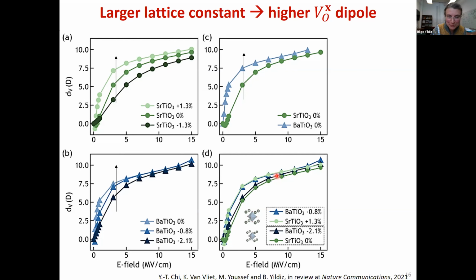So now strain effect on the polarizability under electric field. So the mouthful electro-chemo-mechanical coupling is really embodied in this problem. We're looking at the electric polarization as a function of strain on the defect chemistry of the material. Okay, so that is again the polarization introduced with oxygen vacancy. And now by varying the lattice constant, for example, in strontium titanate, going from compressive to tensile strain, we can clearly see an increase in the net dipole, increase in the polarization. Similarly, by going from compressive to tensile in barium titanate, we see an increase in polarization. Contrasting unstrained strontium titanate to barium titanate, we see an increase in polarization in the latter, the larger lattice parameter counterpart.